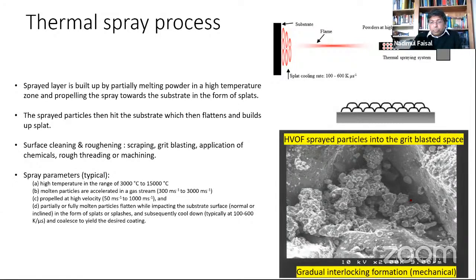What we did is spray and then see how the particles go deep inside those blasted areas, because that forms a mechanical interlocking, and that is what improves the coating adherence with the substrate. So this is the image we tried to capture. Now, the first layer is very important because it is interacting with a different material with different mechanical properties. So the adherence at that point of contact is very important.